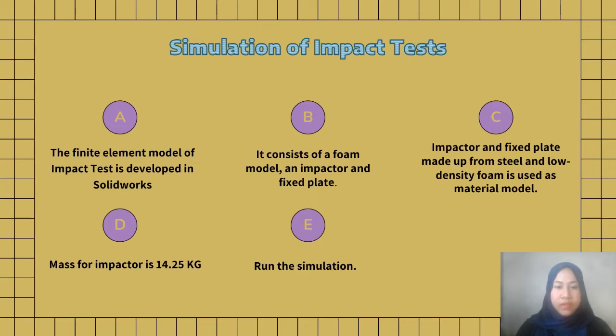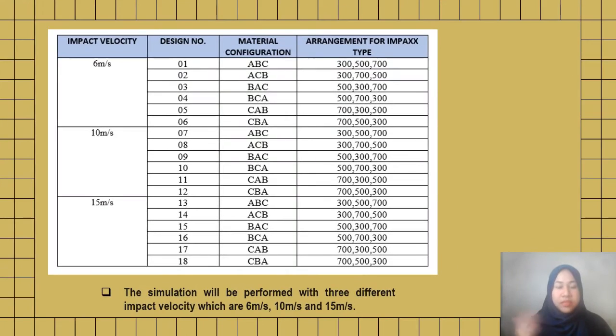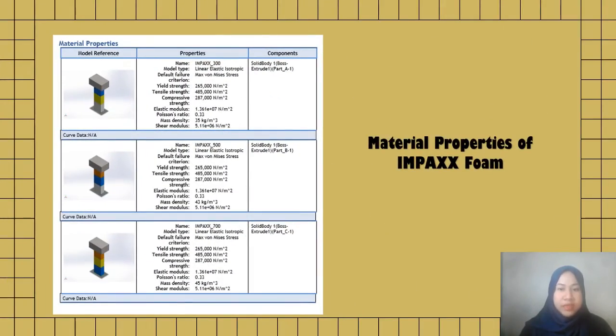After completely filling in the parameters and finishing the meshing process, the simulation for the impact test will be run. Based on this table, there are 18 material designs since the simulation will be performed with 3 different impact velocities, which are 6 meters per second, 10 meters per second, and 15 meters per second. This is the material properties of the IMPAXX foam that has been used for simulation.